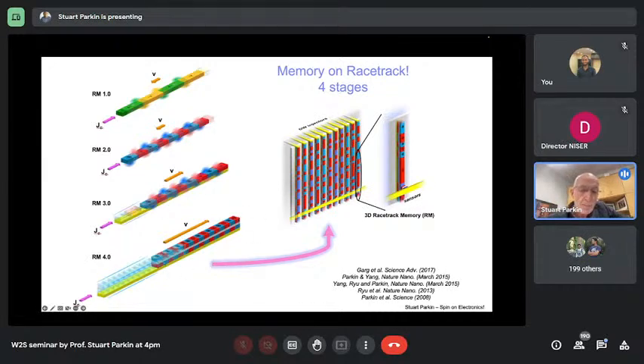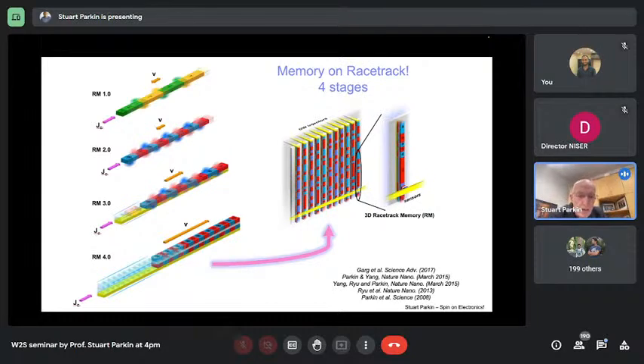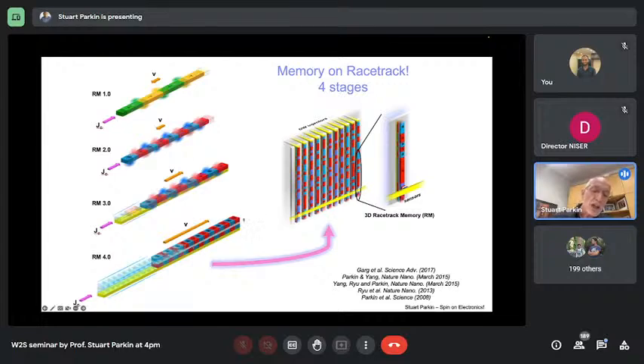And in the racetrack, we did the same thing. We made two identical racetracks, one on top of each other, coupled through an ultra-thin layer of ruthenium, although recently we've discovered a new family of materials which give rise to oscillatory interlayer coupling. These are L10 compounds, in particular ruthenium aluminum. And this ruthenium aluminum is very interesting because it enables us to build the racetracks from other types of materials. But here, this is a racetrack with an ultra-thin ruthenium layer. It's about 7 angstroms thick, and this causes anti-ferromagnetic coupling between the racetrack above and below. So as you see in this cartoon, here we have some red and blue domains, and underneath they have blue and red. And this is because of this anti-ferromagnetic coupling.